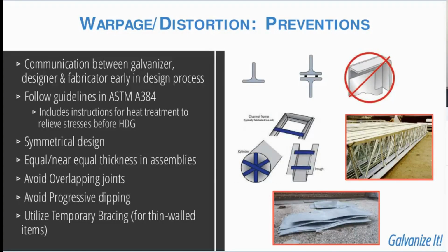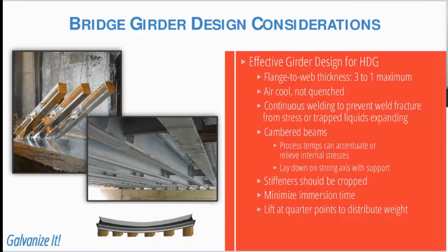The best way to prevent warpage and distortion is to minimize internal stresses overall by following those recommended design practices within ASTM A384. Other mitigations listed in this standard are to use bracing to provide added stability to the part during galvanizing. You can also avoid the combination of thick and thin materials, maybe choosing to combine those after galvanizing, and focus on materials that are symmetrical in design. Where required, a heat treatment before hot dip galvanizing can be utilized to relieve internal stresses in susceptible designs so that they can be successfully galvanized.